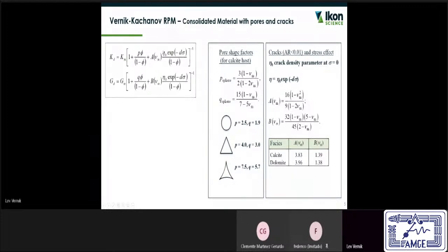But in general, this term right here, this fraction, is the crack density parameter. So when it's multiplied by the specific coefficient, which is a known function of the Poisson ratio, that gives the additional compliance contribution due to cracks or fractures. And that would, of course, lead to a reduction in the bulk and shear modulus and respective reduction in P and S-wave velocity. This is obvious considering open fractures, not cemented.